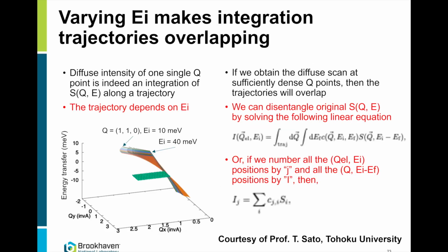And then if you measure at several different incident energies, you obtain an intensity that is a linear function, summed over energy transfer, over the scattered energy. It's basically some linear matrix multiplication of your scattering function and your energy conservation transfer function, and you can actually invert it. So this gives rise to a new technique. When you measure several incident energies, you collect all the data and then you invert them, and you can obtain the original scattering function.